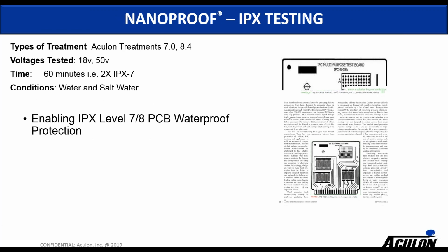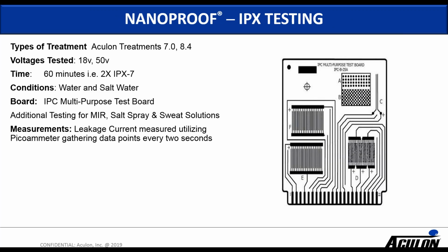The white paper starts off with the IPC multi-purpose test board, which I'm sure many of you are familiar with. We're evaluating two of our more robust treatments, 7 and 8.4. Those treatments are really designed for pretty aggressive immersion environments. So these boards were treated and then dipped for 60 minutes, wall powered at 18 and then 50 volts into salt water. Leakage current was measured every two seconds so that we could detect any current spikes utilizing a picoammeter, a very sensitive voltmeter.